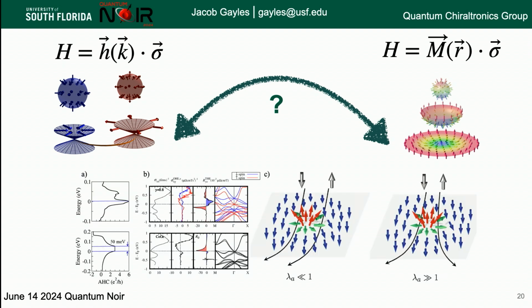And so one case is when we look at skyrmions in the very small limit, or I call it in this case the strong coupling limit, depending on how you look at it. And in this case, what will happen is you can control both spins simultaneously. In the other case, in the large limit or the weak coupling limit, the spins of the electrons will diverge. And of course, the big interest is what happens in the middle, which is the hard physics, right? What you can see here are actually some results from my PhD, is that what started a lot of this is that some of these materials, which we're not interested in for this part of my PhD, but the Weyl actually pops up here, and that's where you get the largest topological Hall effect for these materials.